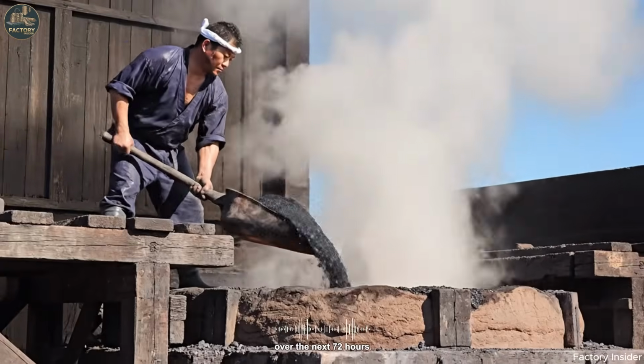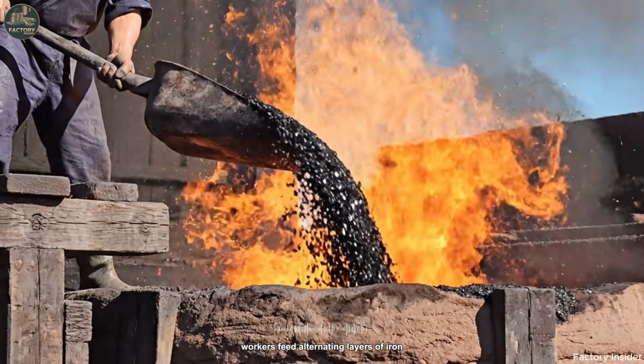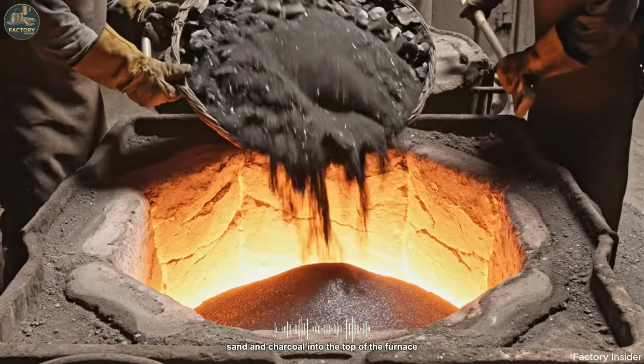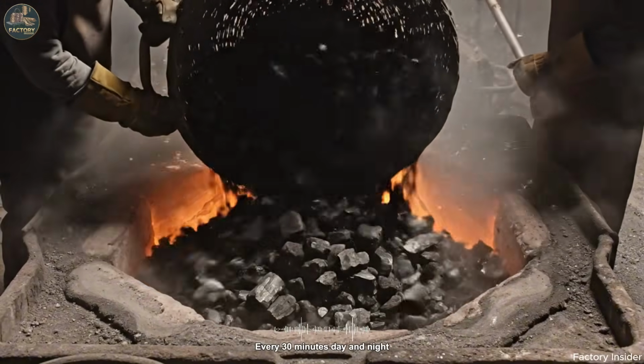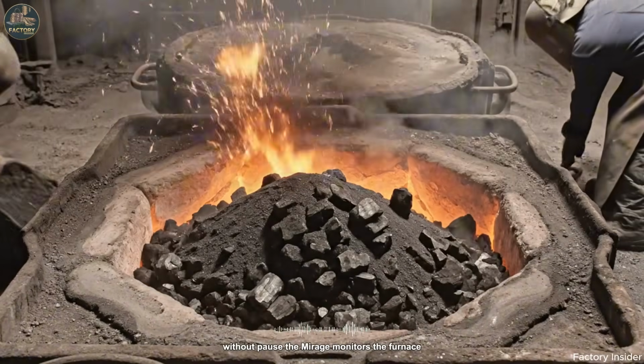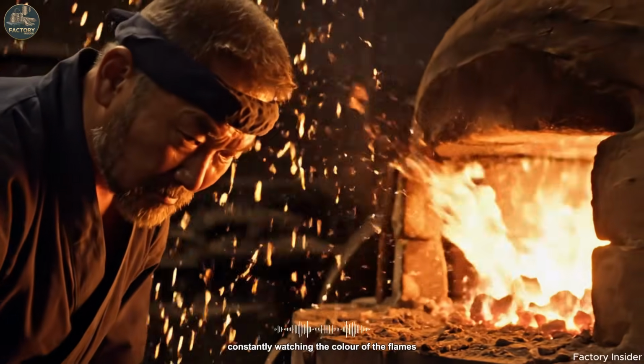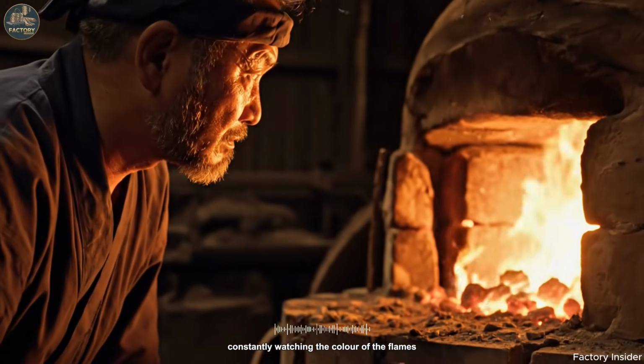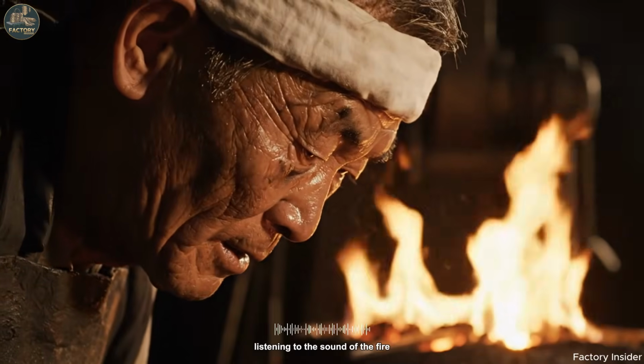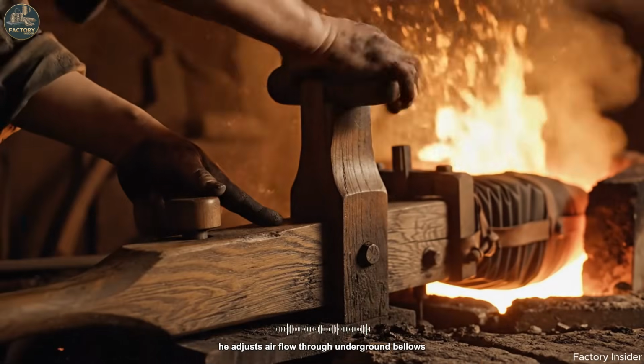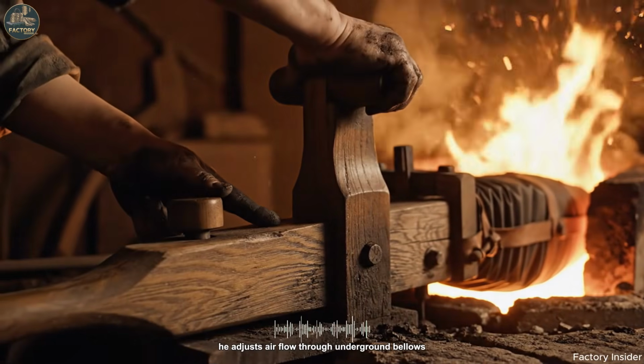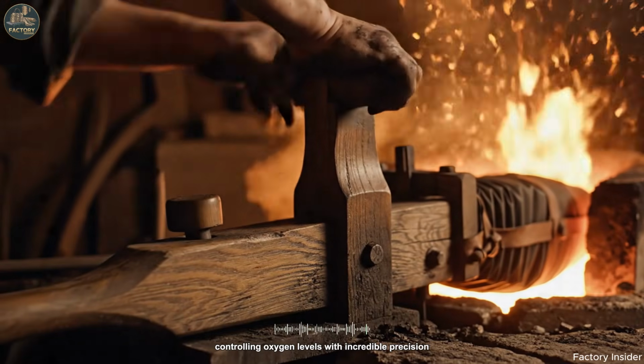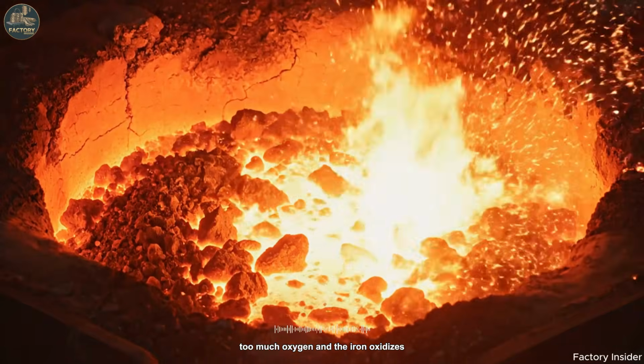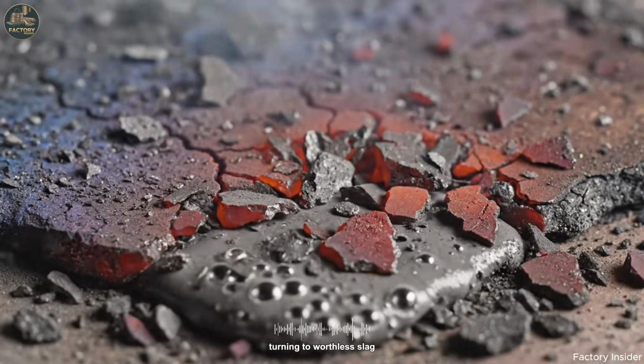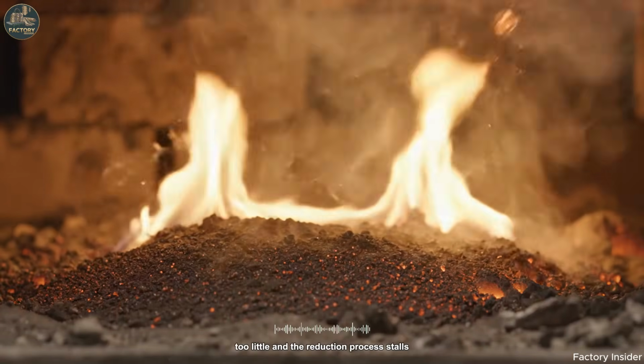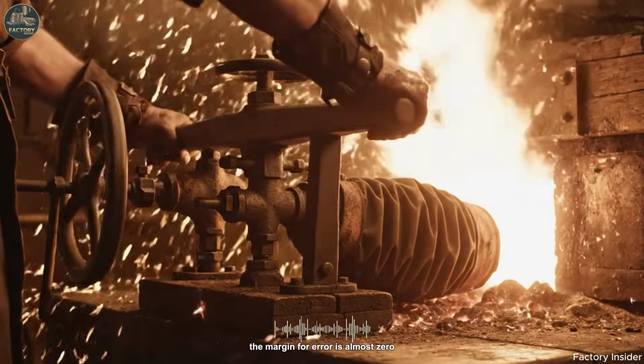Over the next 72 hours, workers feed alternating layers of iron sand and charcoal into the top of the furnace, every 30 minutes, day and night, without pause. The murage monitors the furnace constantly, watching the color of the flames, listening to the sound of the fire, even smelling the smoke. He adjusts airflow through underground bellows, controlling oxygen levels with incredible precision. Too much oxygen and the iron oxidizes, turning to worthless slag. Too little and the reduction process stalls. The margin for error is almost zero.